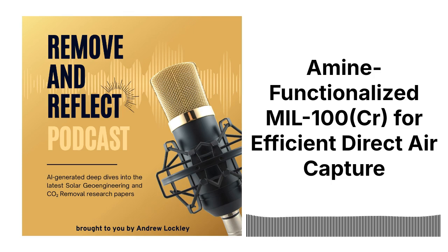Exactly. So to sum it all up, what are the main takeaways about using amine-modified MIL-100 Cr for DAC? Well, I think it's safe to say that MIL-100 Cr modified with PEI has a lot of potential. Okay. It had the highest CO2 capture capacity, great cyclic stability. It actually worked better with humidity. Yeah, that was a big surprise. It was. And it was the most resistant to oxidation. PEI is the clear winner.